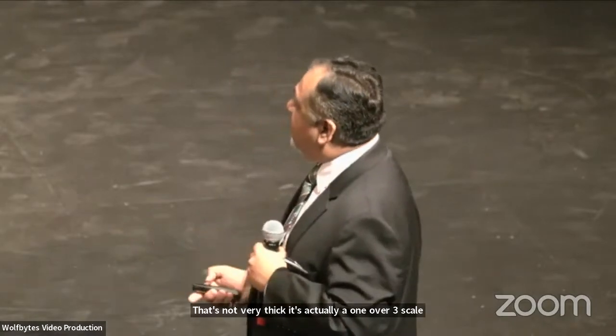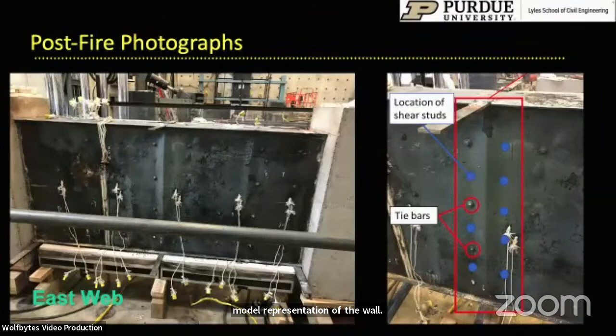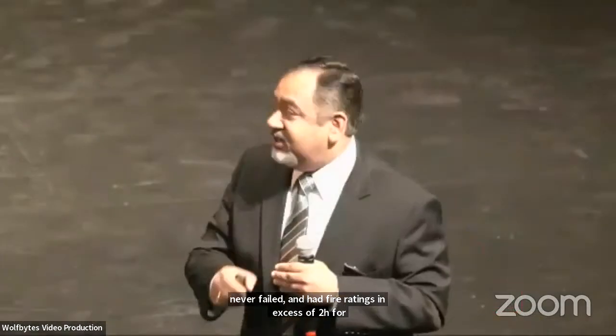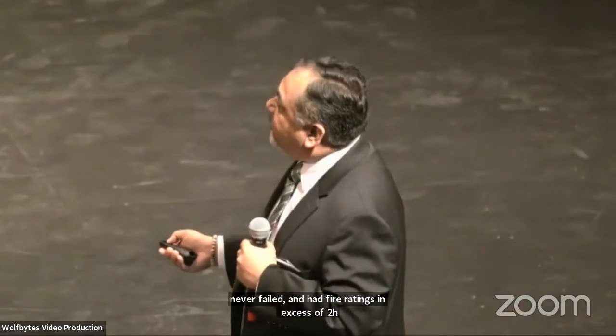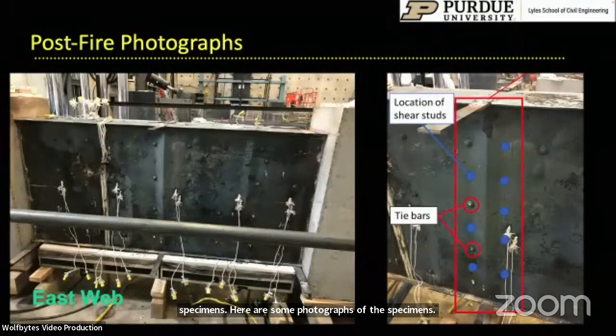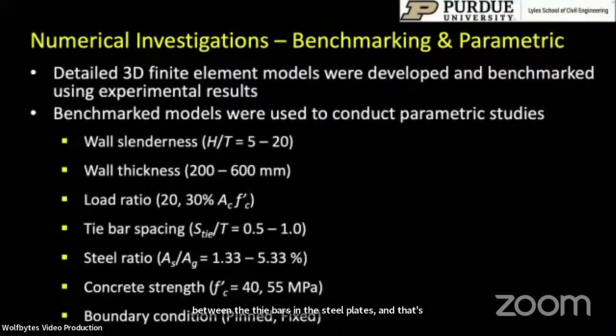So we found that the concrete provides a very strong heat sink for the system, to the point where, in spite of all the load that had been applied to it, the specimens never failed and had fire ratings in excess of 2 hours for the 1/3 scale 9-inch thick specimens. Here are some photographs of the specimens. You can see the local buckling that has occurred in between the tie bars in the steel plates. That's a close-up of that, locations of shear studs and tie bars and the local buckling in between.